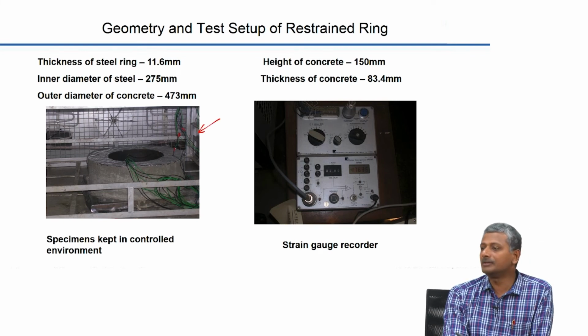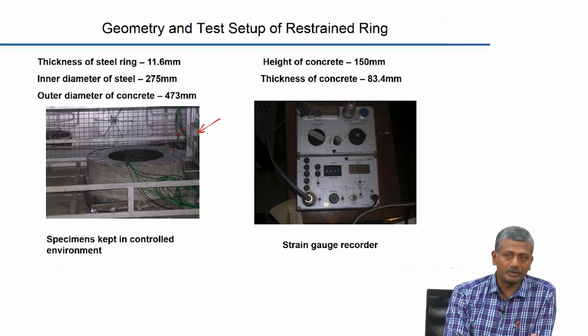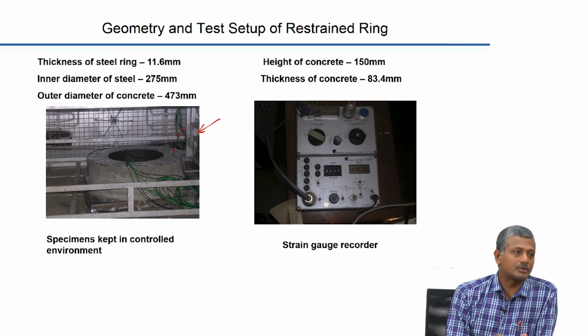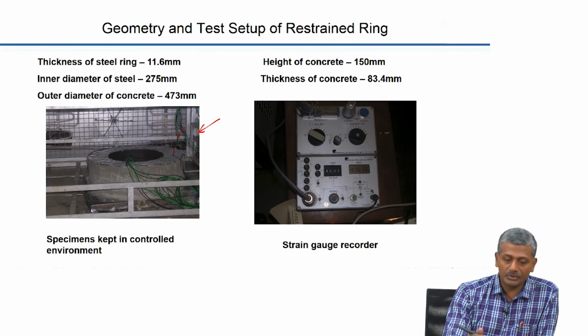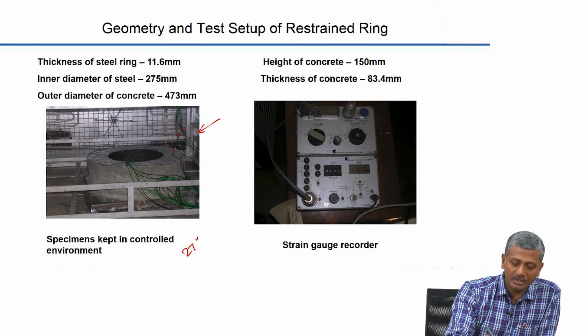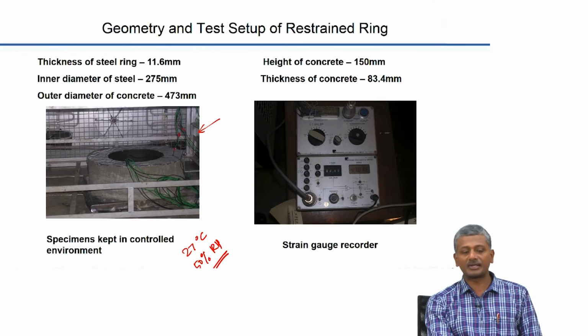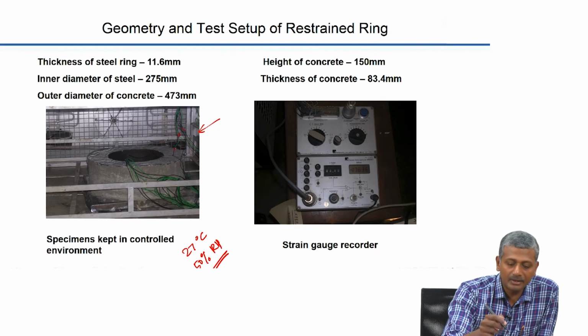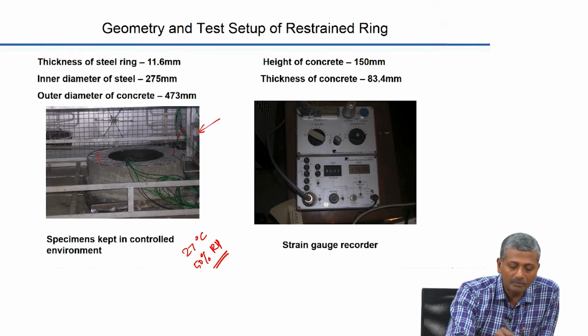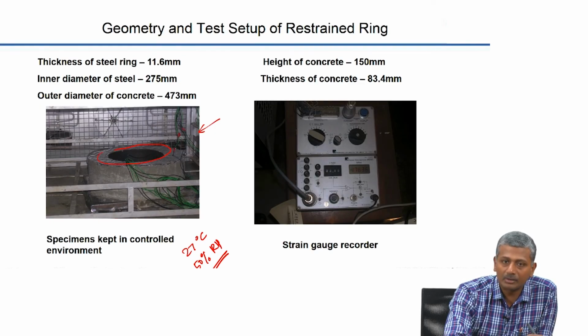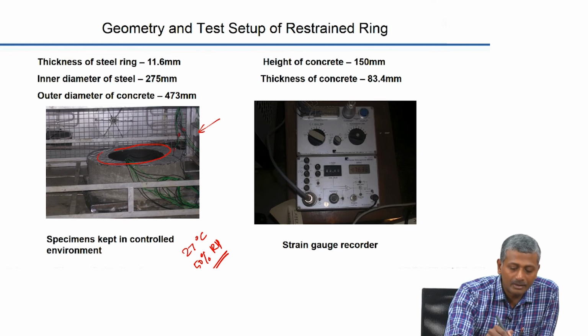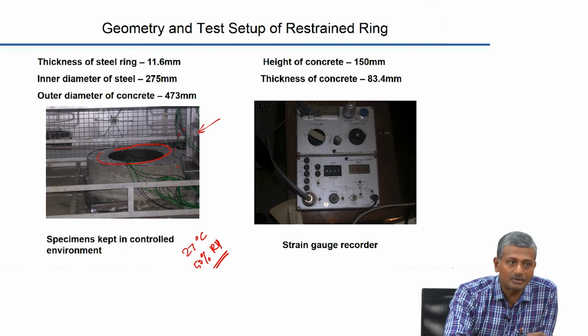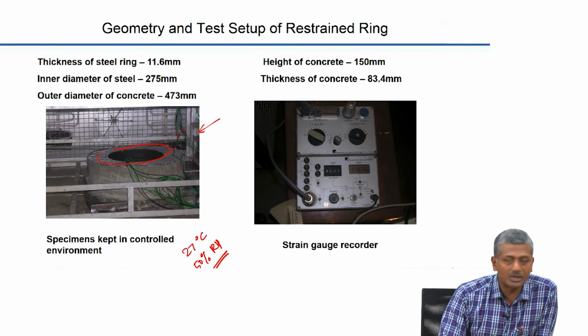This is the same environmental chamber that we used earlier for the plastic shrinkage study. Here this has to be done in a temperature and humidity controlled environment again, because depending upon the temperature and humidity, the extent of shrinkage that happens in the concrete will vary. The measurements were done at 27 degrees Celsius and 50% relative humidity. This control has to be maintained using the environmental chamber, and this is the ring here. You see the top of the concrete ring has been completely sealed, and the circumferential surface of the ring has been exposed to start drying out.